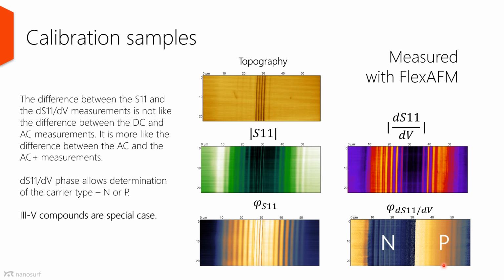Here I would like to say that dC/dV works well for silicon or germanium, but for the III-V semiconductors not so well, because there is always a layer of arsenic below the oxide, and this layer of arsenic is metallic. So the extraction of the information about the dopants from the dC/dV in III-V semiconductors is difficult. An S11 measurement would work better for III-Vs.